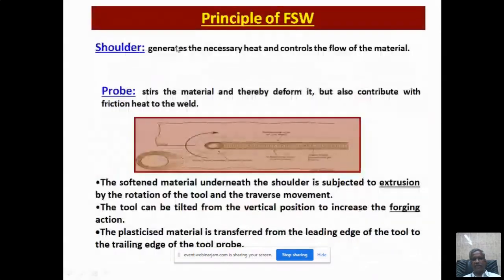So the shoulder produces maximum heat. 2/3 of the heat will be produced by the shoulder, obviously because it has a large diameter. The probe, that's the pin, will produce minimum heat, but it's not for heat production. It is for stirring purpose. The pin is mainly for stirring the material. So this process, though it comes under welding, is basically a metal forming process.